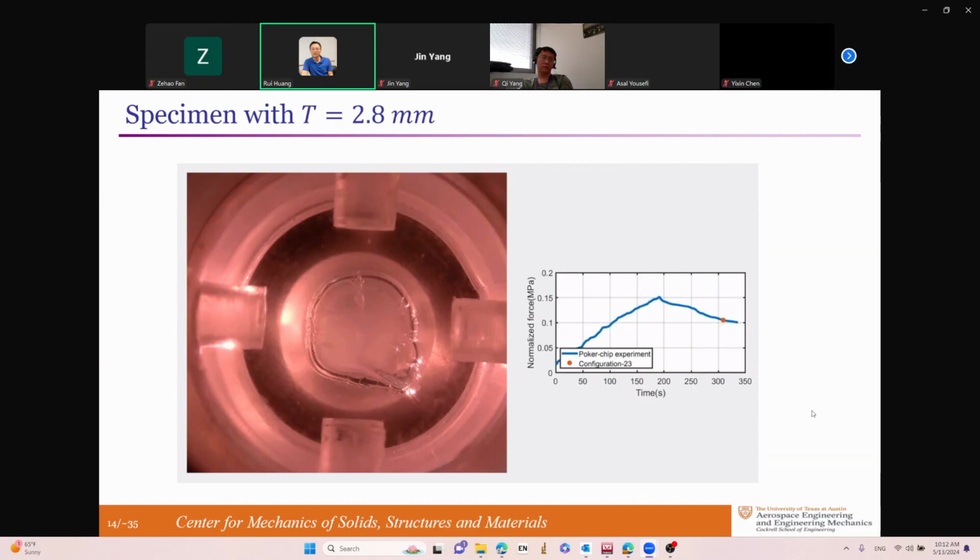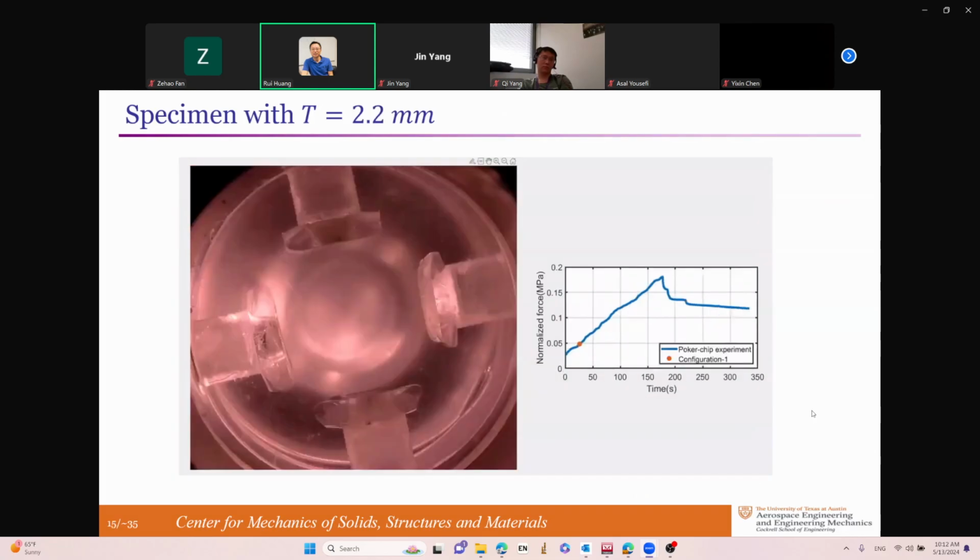And then I'll show you some X-ray images where we did real-time observations to indicate that the nucleation occurred in the interior. So the nucleation, if you notice, didn't occur at the center. It occurred biased at some distance from the center. And that's going to be important. Then there was one nucleation which continued to sweep through the entire specimen. Now let's change the specimen thickness a little bit more.